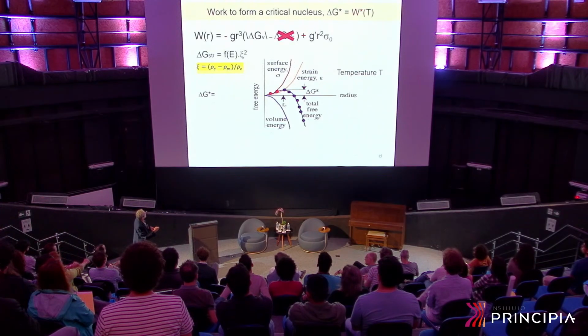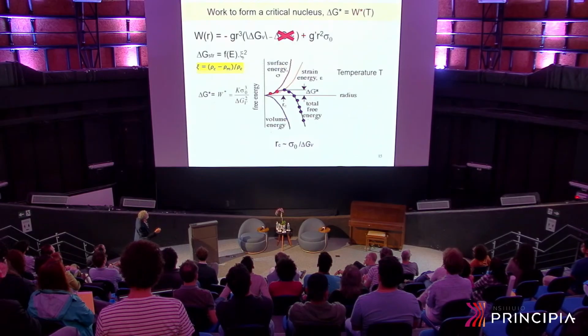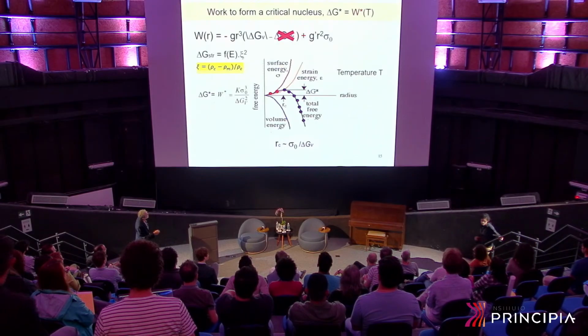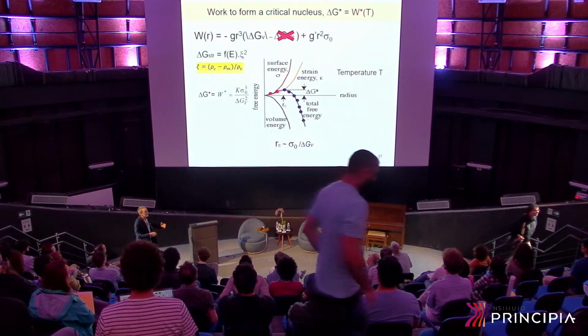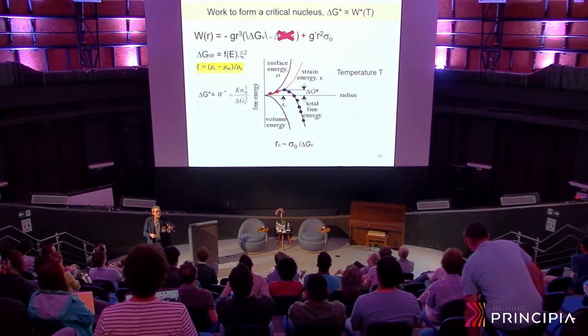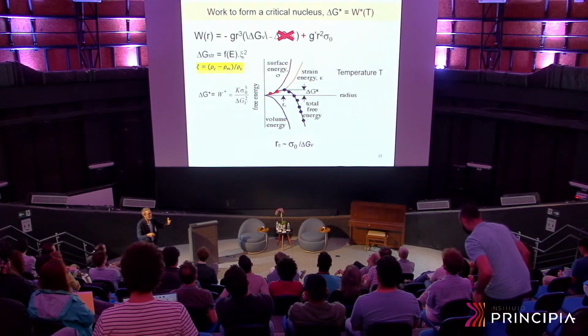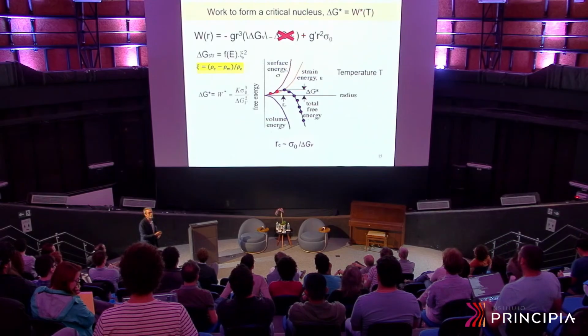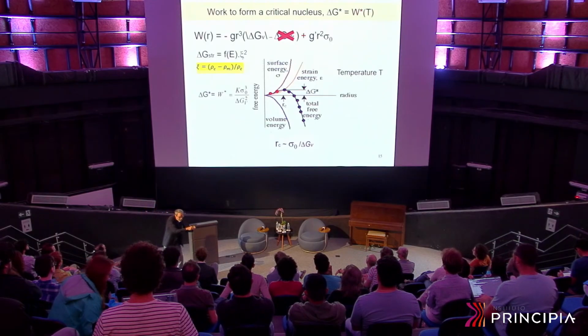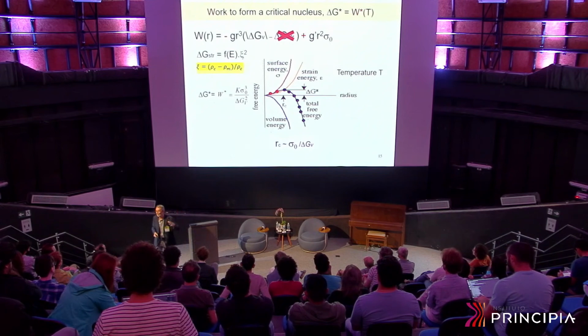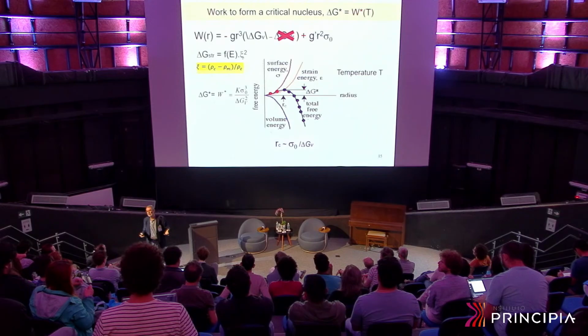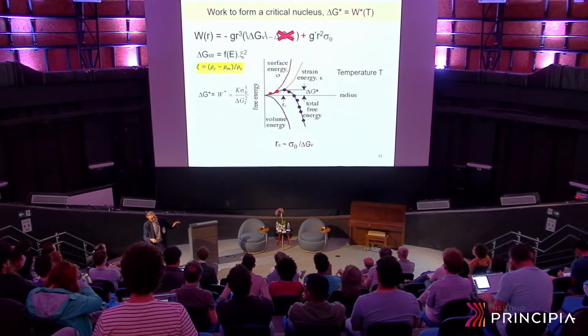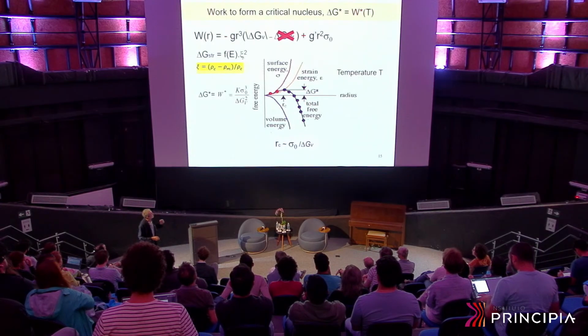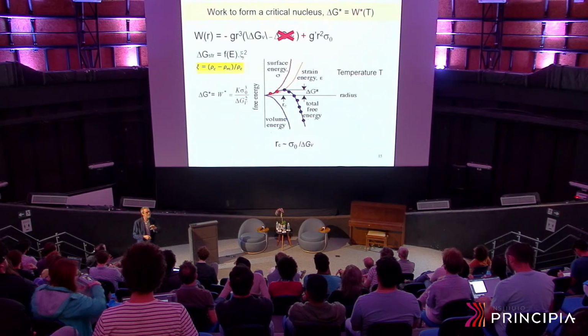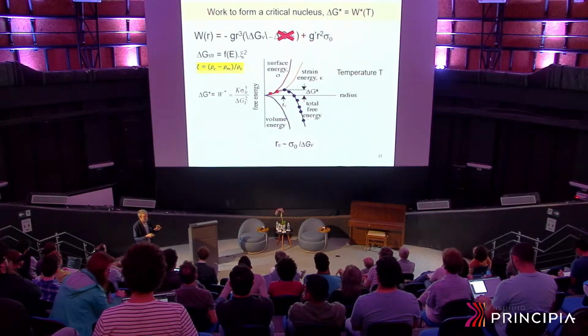So the critical radius here is just the interfacial energy divided by delta G. Delta G is the free energy difference between the liquid and the crystal. It can be measured by calorimetry. The interfacial energy cannot be measured. There is no equipment to measure the interfacial energy between a critical nucleus of a few angstroms and its surrounding liquid. You can calculate it theoretically with several assumptions, or you can fit nucleation rate data to the final equation to get the interfacial energy, but in principle it's unknown. It's an unknown parameter, unfortunately.